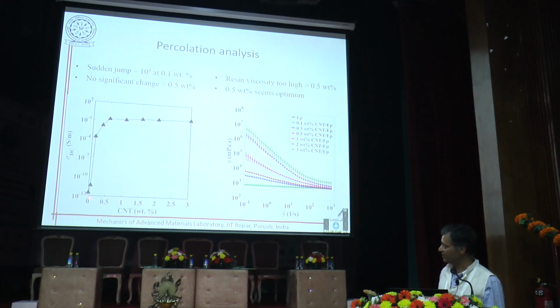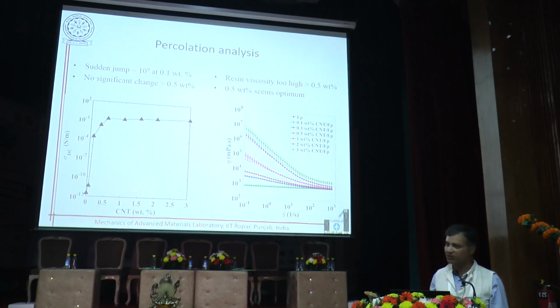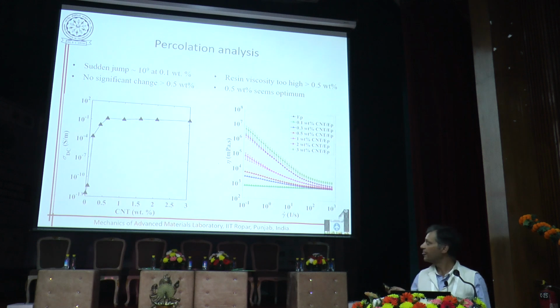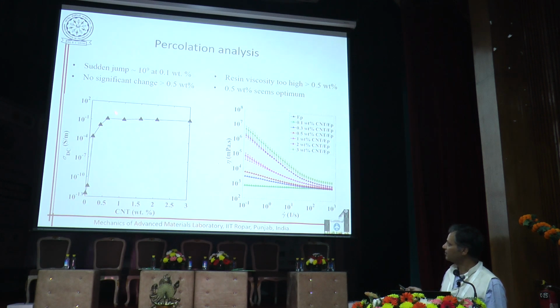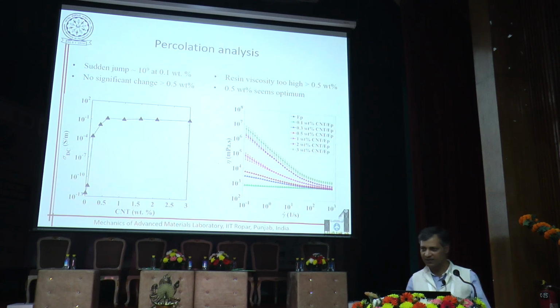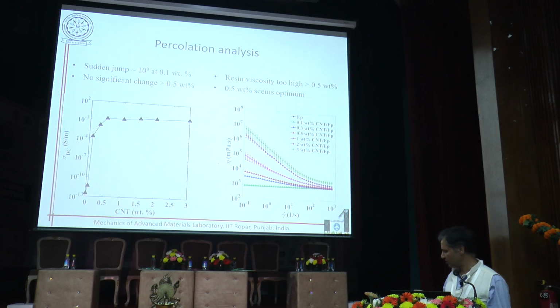DC conductivity shows the typical power law behavior. When there is a percolating network of the CNTs within the epoxy, there is a sudden jump in the electrical conductivity of the order of 10⁸, and beyond that it is almost flat. That means the conductivity is not changing. So there is no point in adding more CNTs beyond that point, because we are unnecessarily making the system more viscous. As you can see here, the viscosity up to this point is more or less comparable, but the moment you go above, the viscosity increases quite a lot.